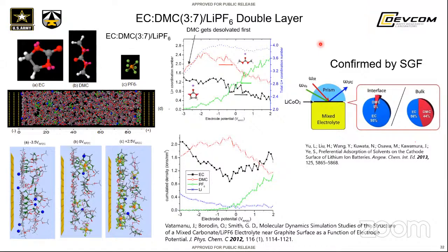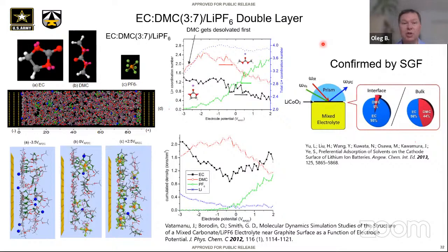What I typically look at is the residence time of the lithium next to solvent, next to anion. So the run should be longer than the residence time. So to sample, residence times, for example, in EC/DMC are about 100 picoseconds at room temperature, so that you can equilibrate, and about 200 picoseconds for the PF6 at higher concentration. There, if you raise the temperature, you are doing fine, you can equilibrate.